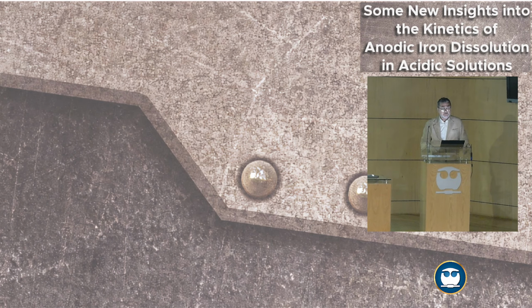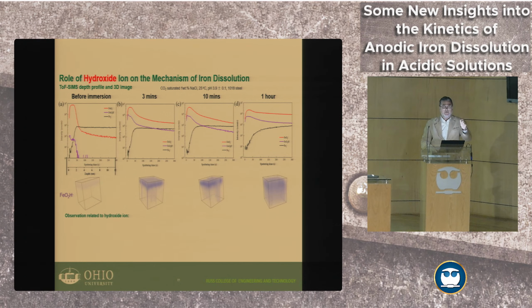It doesn't matter. And then they say, well, let's look at this hydroxide. There has to be now a serious amount of hydroxide on the surface, iron hydroxide, if that theory is correct, the Keddam theory, the theory my students use. There has to be a compound that has hydroxide in it there. And sure enough, there was no hydroxide more or less to start with. And then after 3 minutes, it showed up, and then 10 minutes even more, and then after 1 hour, there was this hydroxide. Wherever there was iron, there was hydroxide. So here's your independent proof.